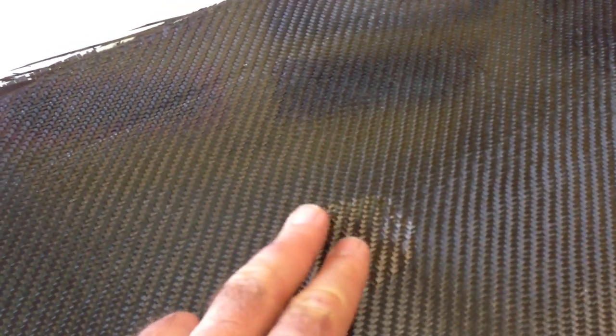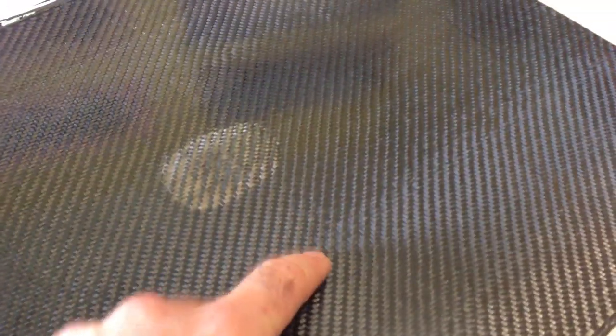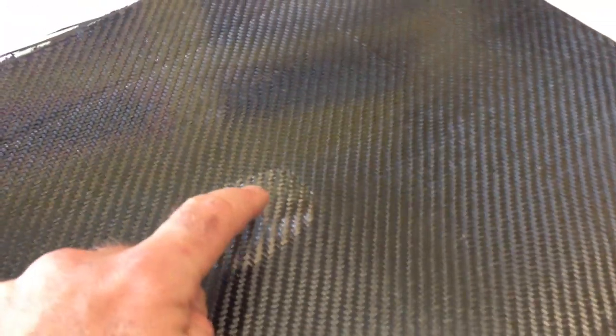And I do have a dual stage vacuum pump, which I'll try later on before we do the final product. And that will pull a better vacuum and prevent this from happening. At the same time, it will actually perforate the core material just by putting holes in it at about 100mm intervals. Technically those holes will fill with resin and will add a bit of weight, but it doesn't matter too much. The holes can be very, very small. It just has to allow airflow.